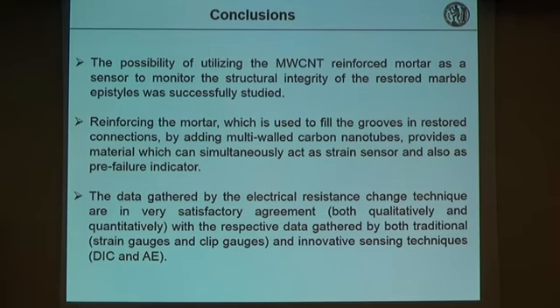I'm not going to stay to recap, just two very important points: it seems that the use of multi-walled carbon nanotubes to reinforce the mortar can actually develop a material that can act as a strain sensor and pre-failure indicator. And also we're very happy because the data of the electrical resistance change are in very good agreement with traditional techniques, with the results of the clip gauges, the strain gauges, and also with the results of the DIC and the acoustic emission. Thank you very much.